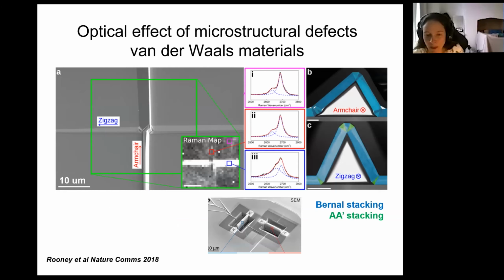Okay, so we can see what's happening within these crystals, because we can look at the effects of the changes in microstructure on the optical behavior. So here we've got a Raman map of a zigzag deformation, with the displacement of slip along the armchair direction. For a deformation feature along the zigzag direction, we can't maintain this perfect stacking in graphite all the way through. We end up with regions that are not ABA, but which contain AA stacking. Even though that's very unfavorable, the slip requires those within the system, and these regions of AA stacking create changes in the Raman signal, so we can use this to distinguish between the armchair and zigzag type kink band defects.